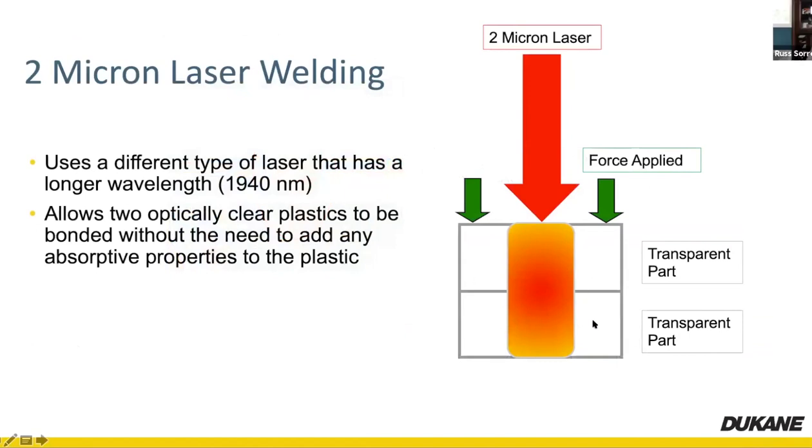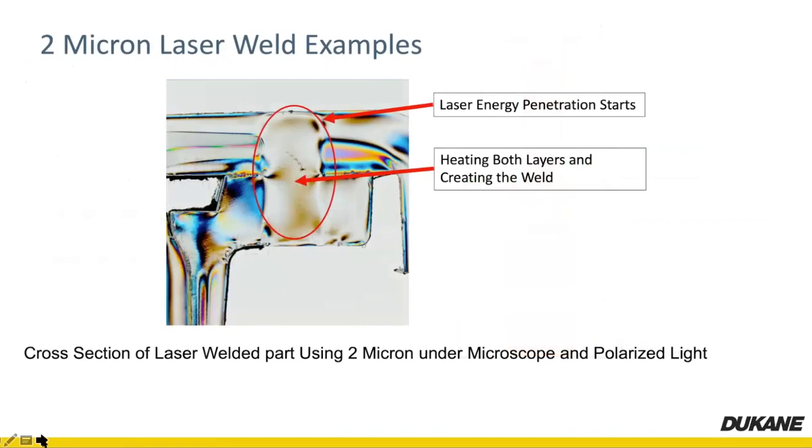So how does the weld take place? It's not welding like this; it's still the laser going down. Basically, we take two parts and we clamp them under a piece of borosilicate glass usually, or some sort of laser transparent clamping fixture. And that holds them together. Then the laser produces a melt all the way through the part. So the glass and the fixture kind of act as a sandwich to keep the material from bubbling up on the top. So we get a smooth weld, and then we produce a full melt through those surfaces. I see. Very cool. Yep.